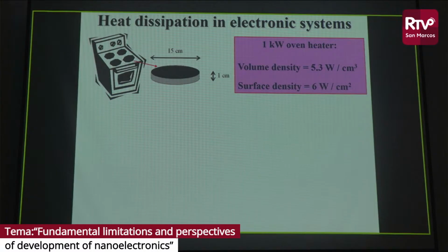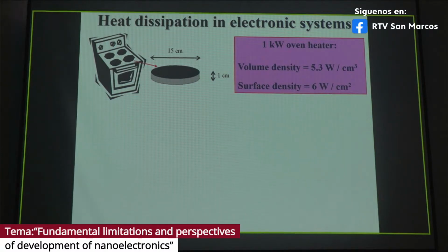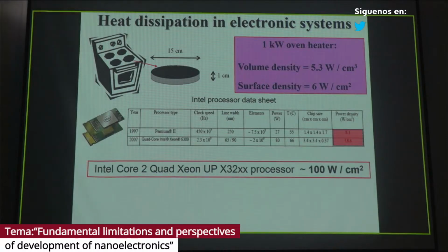Now let's turn to another technological problem which bothers industrial producers even more than quantum mechanical tunneling. If I made my home exercise correctly, I calculated that for a conventional kitchen heating element with 1 kilowatt power, the volume density and the surface density are about a few watts per cubic centimeter, or about 6 watts per square centimeter. Now what about processors? This level was already approached about 20 years ago. And now in modern Xeon processors it is more than 100 watts per square centimeter.